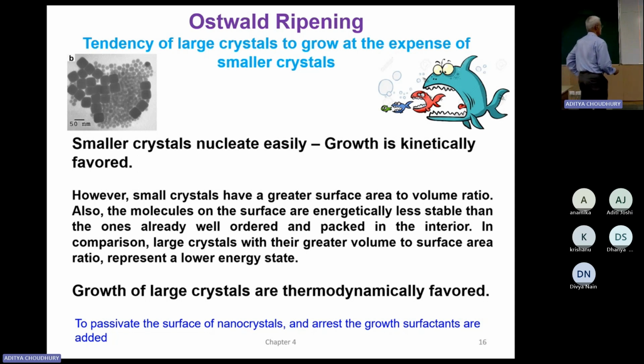Now, why is this happening? Smaller crystals nucleate easily, growth is kinetically favored. So what is really happening? Take a look at the surface area, take a look at the bulk, the ratio of the surface area to the volume. For a big crystal, it is small. The surface area is small, volume is big. So it is not the surface energy that's going to interfere, because you already have lots of delta H in the bulk.